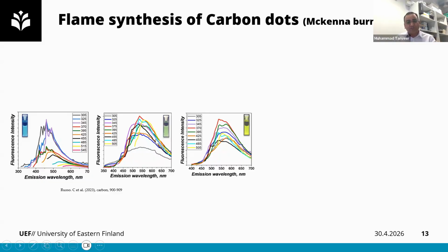And these yellow green dots are basically large fragments of polyaromatic hydrocarbons, because these polyaromatic hydrocarbons fuse together, conjugate together, and form the large clusters. So as the sizes of these nanostructures increase, their band gap will decrease, so that they can be active in visible light. So they exhibit fluorescence in a green region. And then these yellow dots are basically due to some size related features, defects, and also some functional groups, some chromophores on the surface of carbon dots, which also contribute to the photoluminescence features of carbon dots.